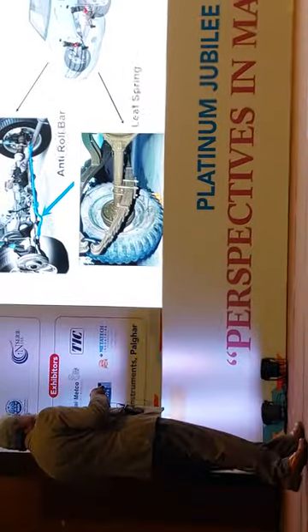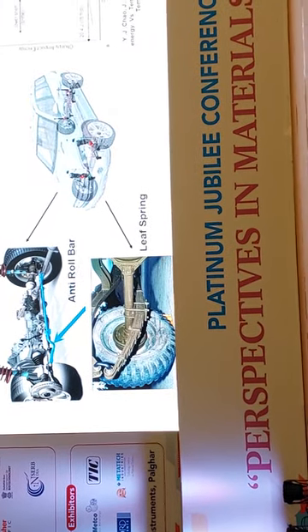We are looking at anti-roll bars, leaf springs, and other candidate materials that exhibit ductile-to-brittle transition. A classic example was published in SAE in 2005, dealing with CVN impact energy versus temperature and ductile-to-brittle transition temperature. Most DBT papers focus on Charpy or Izod impact tests, and there is even a misconception that DBT is synonymous with impact testing and nothing else.